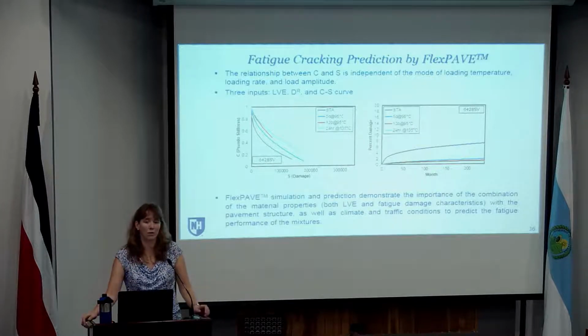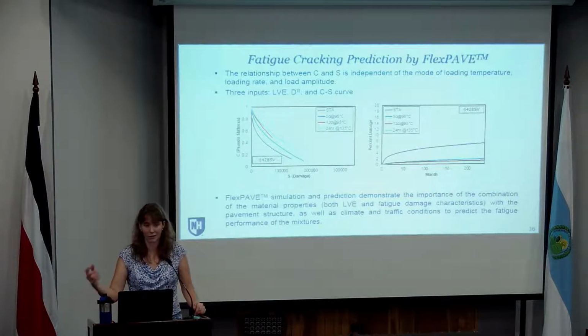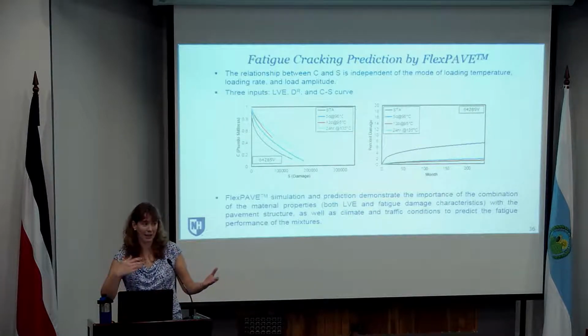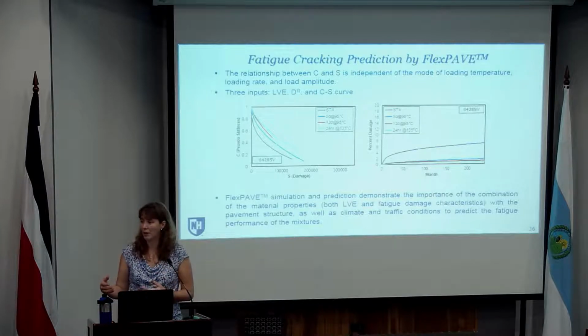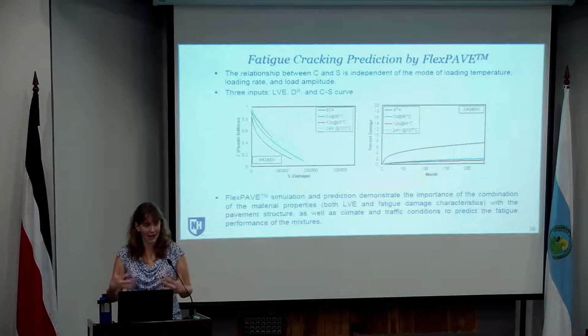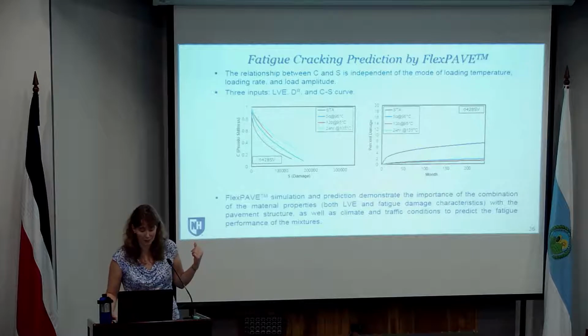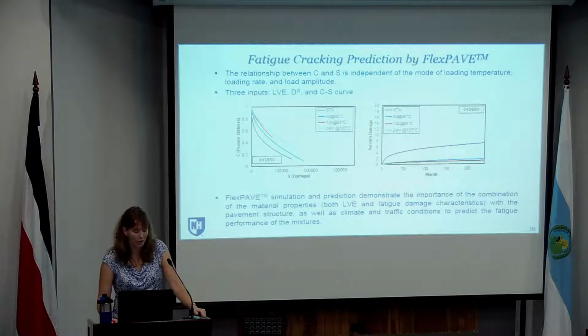So you might get one picture looking at the fatigue characteristic from a laboratory test and say, okay, yeah, this mixture is better than the other. But then once you put it into a performance model and really look at how that material is going to perform in a pavement structure, you can get a completely different picture. And this is just an example here. What I'm showing in this figure on the left is some of the fatigue curves, the characterization that comes out of the test results. But really what I want you to focus on is this figure on the right, which is looking at damage over time for the different conditions. And you can see, with the particular pavement structure that we used in this evaluation, that short-term age material shows to be the worst.